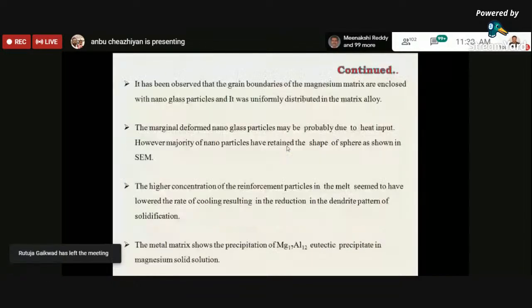This needs to be avoided, because of this the machinability properties cannot be carried out. So improving the surface properties needs to be considered, and that is another area in this research work. From the microstructures, it has been observed that reinforcement particles are uniformly distributed through the cross section. It has been noted that the grain boundaries of the magnesium matrix are enclosed with nanoglass particles, uniformly distributed. We have seen some marginal deformation of glass particles.